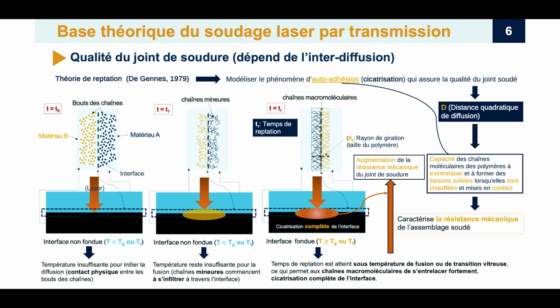Engineers measure this using something called the mean square diffusion distance of the chains. If that distance hasn't reached the necessary threshold for the specific polymer, you don't get full strength. Complete interfacial healing means that diffusion distance is substantial, the entanglement is complete, and the joint strength is fully recovered. The interface effectively vanishes under stress.